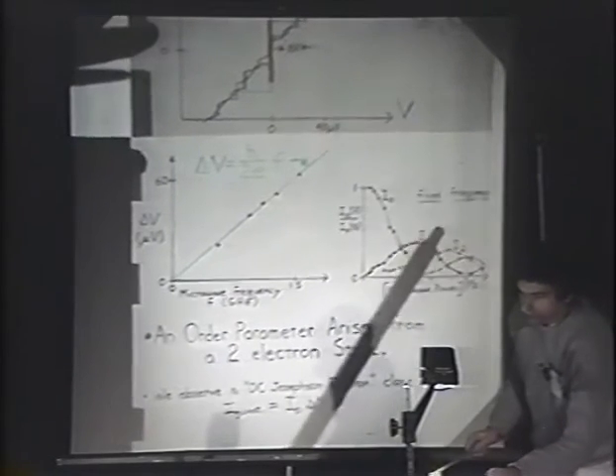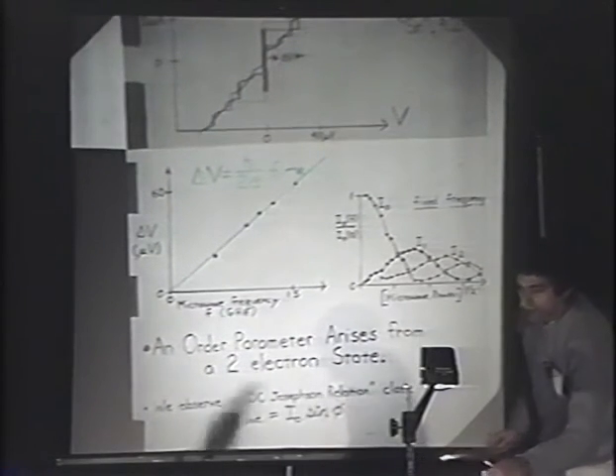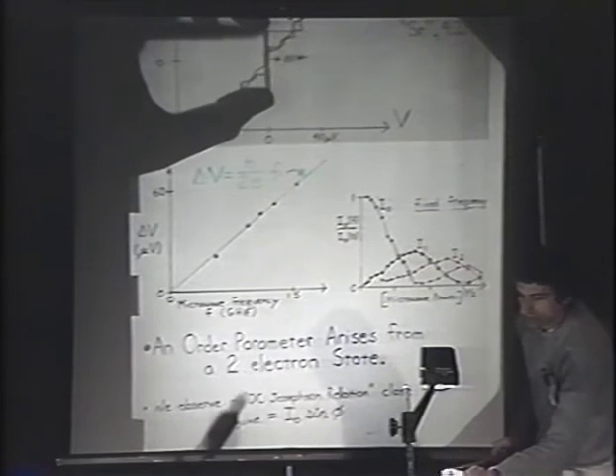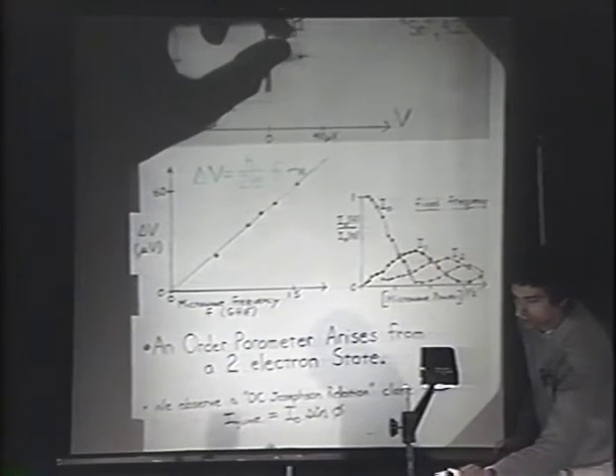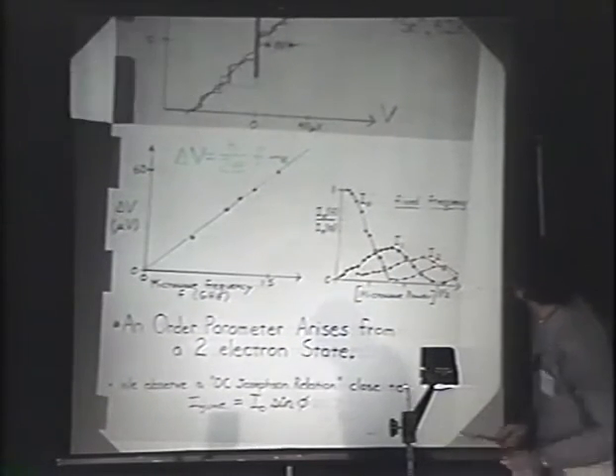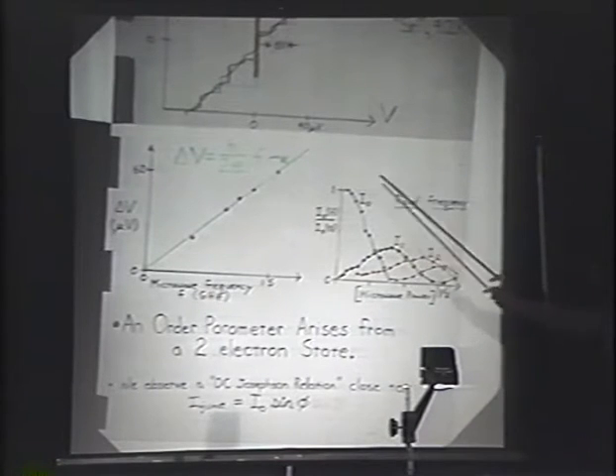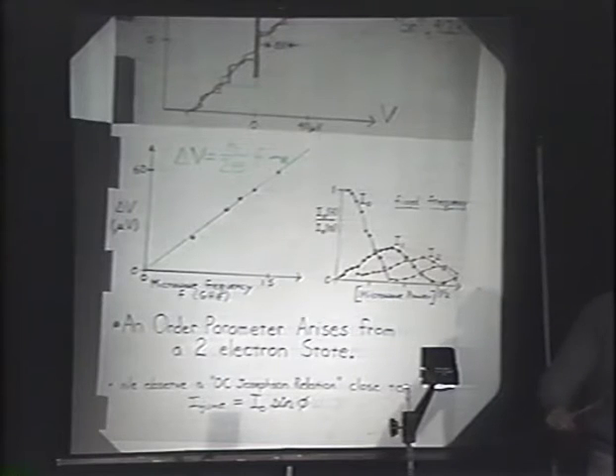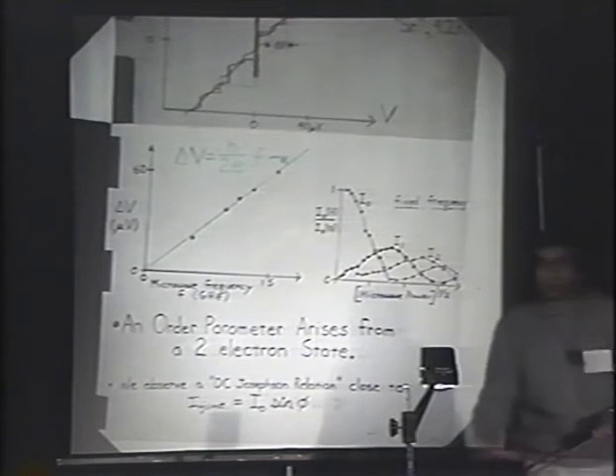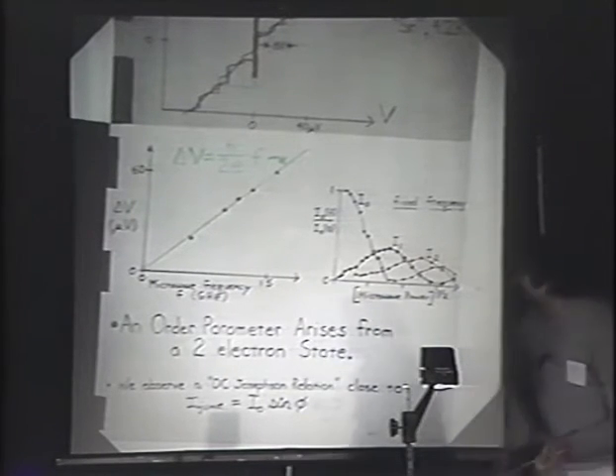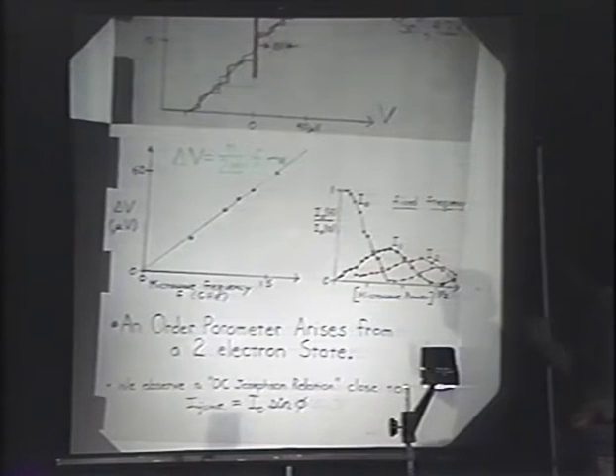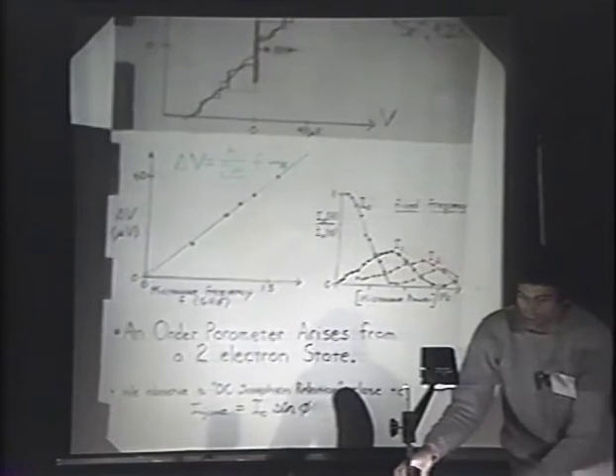We can also sit at a fixed frequency and measure the modulations of the 0 step, the first step, and the second step. We get some Bessel function behavior that's in quite good agreement with what you would expect from normal weak link behavior. This indicates that a DC Josephson relation, at least close to sine phi, is obeyed in this system.